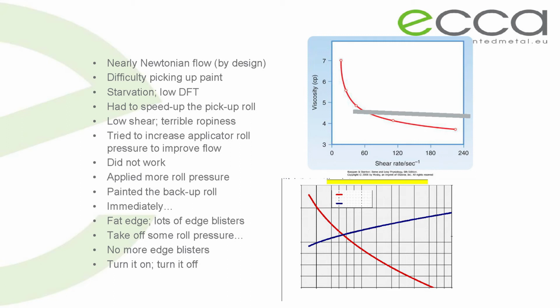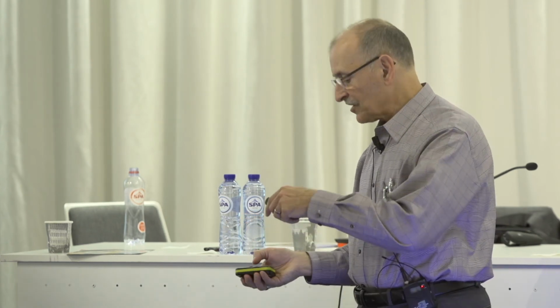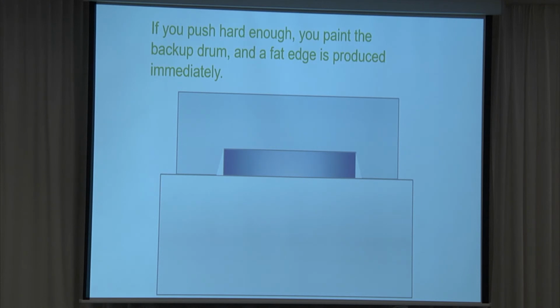So in my opinion, that bead is put on the edge as a result of either painting the backup roll and some of the paint is coming back on the edge, or even if you don't paint the backup roll, you can just visualize this, right? Sorry, but there is paint on the roll right there. So I think what's happening is, just because of probably some kind of viscoelastic effect, that paint ends up being snapped back onto the roll to form the bead.